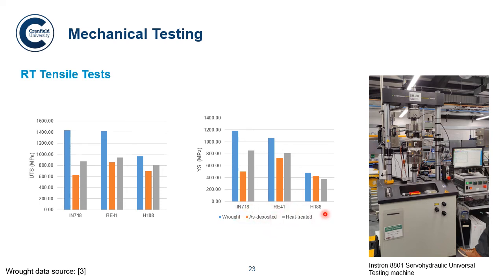And then we've got our heat treated samples, which is the WAAM material which has been heat treated, in grey. If you look at UTS here in this graph, you can see quite a big difference between the wrought strength and the as deposited strength. And then when we heat treated 718, we see quite a big jump up in performance, but not as much of a jump up to the wrought strength, which is a little bit disappointing.